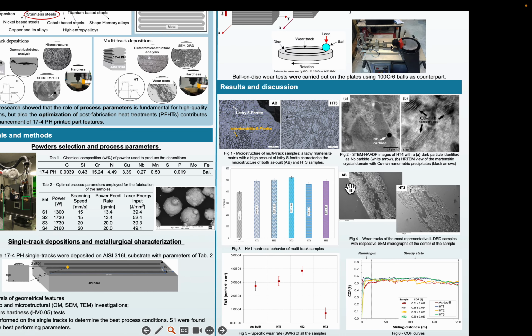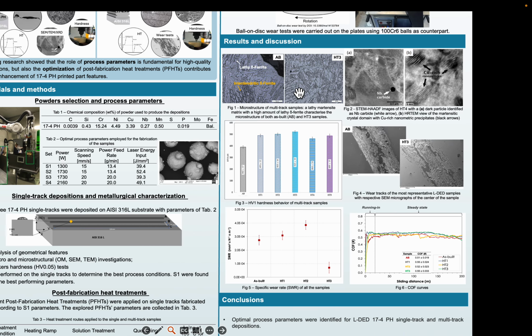From the results, as we can observe in these micrographs, the characteristic martensitic matrix with presence of delta ferrite across the as-built sample was identified, specifically in the grain boundary depositions and interdendritic delta ferrite, compared with the treated samples, as an example in this case the HT3, that shows a minimum quantity of delta ferrite among the matrix due to the direct aging effect.